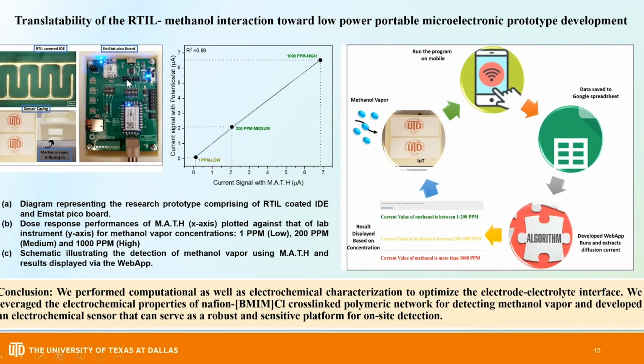So I have shown the last part over here, wherein this is the research prototype that was used. This is the electrode design that we designed in-house in our lab. We use the EmStat Pico board as the potentiostat, and this was the device box that we used such that the methanol vapor was diffusing inside from here. We then compared the dose performances of MATH, that is our prototype, with respect to the benchtop potentiostat, and we got an R square of 0.99 for the three doses that we were looking at, low, medium, and high, such that the benchtop potentiostat and our device showed similar response.